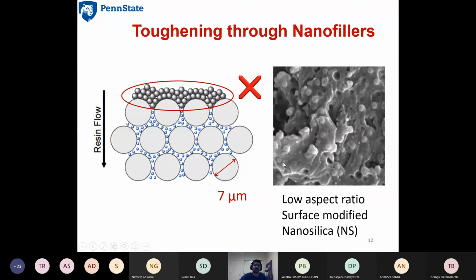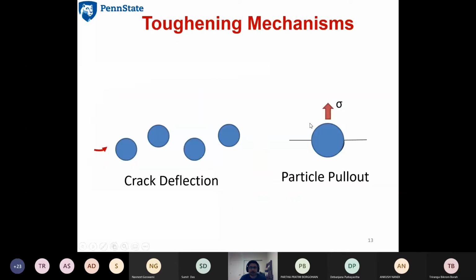These particles had a diameter of 142 nanometers. So these were really, really small particles. You can see these particles here on the right. These small particles have a size of 142 nanometers. So how do these nanoparticles improve the toughness of the material?